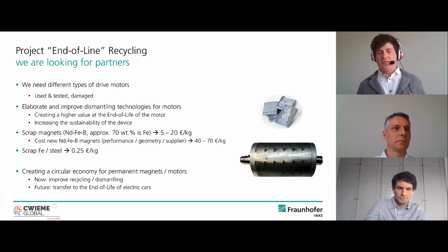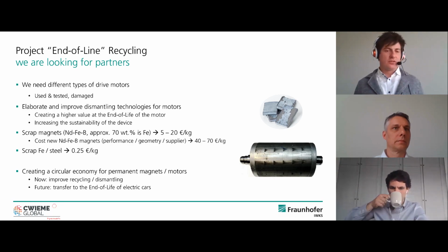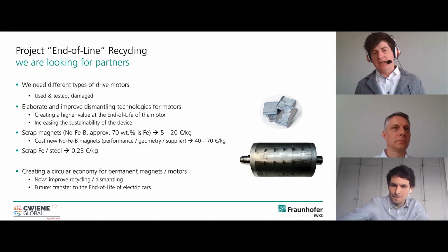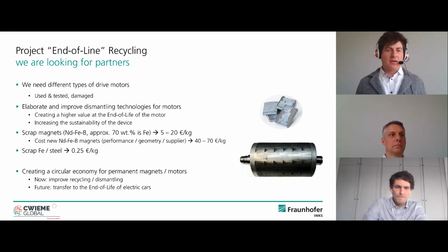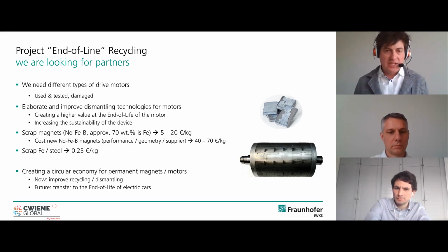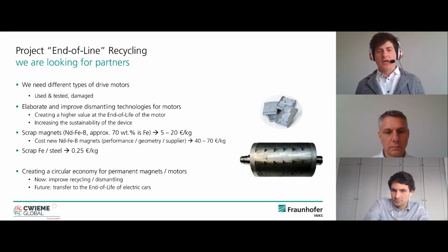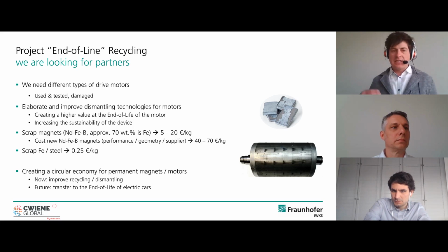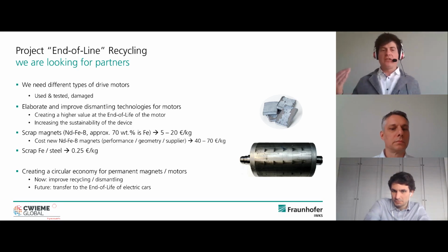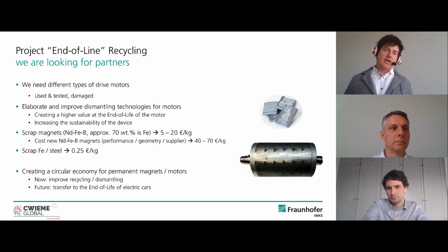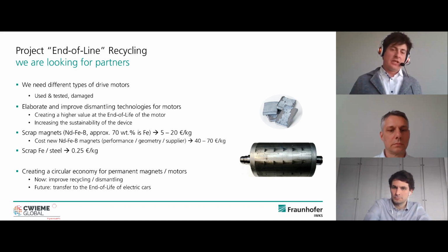At the end of life, you will get something nowadays, the market is not really there yet, but you will get something like 5 to 20 euro per kilogram for scrap magnets, also dependent on the composition. And if you recycle it with steel, and like I showed before, 70% of the magnet is iron, you will get 25 cents per kilogram. So I think there is a value which can be gained, and in terms of sustainability, it is feasible to do.